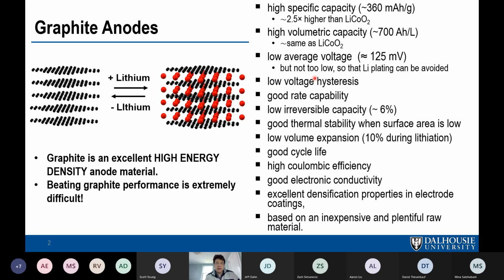And having all these characteristics come together, high capacity, 2.5 times higher than the cathode, volumetric capacity matches the cathode almost exactly, so that the electrodes are about the same thickness, they're well paired. Has a very low average voltage, which is perfect for a negative electrode. It's not too low, otherwise you could get lithium plating. Kinetics are excellent, rate capability is excellent, irreversible capacity is quite low, thermal stability is good, cycle life's great, Coulombic efficiency is high. It's a pretty inert material, doesn't react with much.